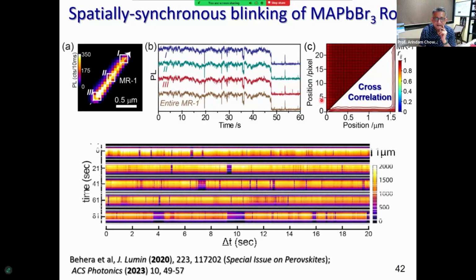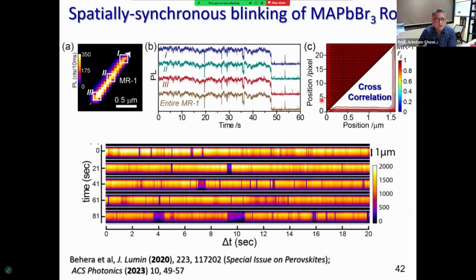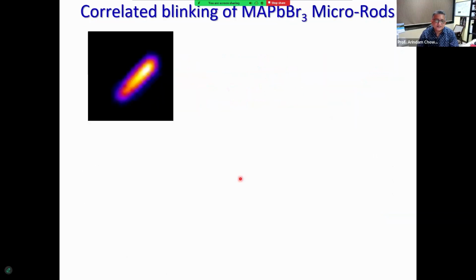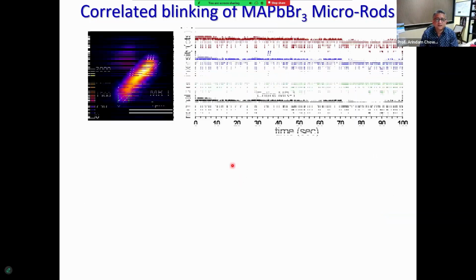It's highly, highly correlated. If I take the entire rod, take the intensity along the long axis of the rod, and plot from a movie, one frame adjacent to the previous one, and keep doing it for the entire duration, you see this kind of behavior. Each of these rows here, 1, 2, 3, 4, 5, represents a rod. And you can see that over the entire space, the blinking events are spatially correlated. So it's not something that is only true for this disk. This also seems to happen for these rods.